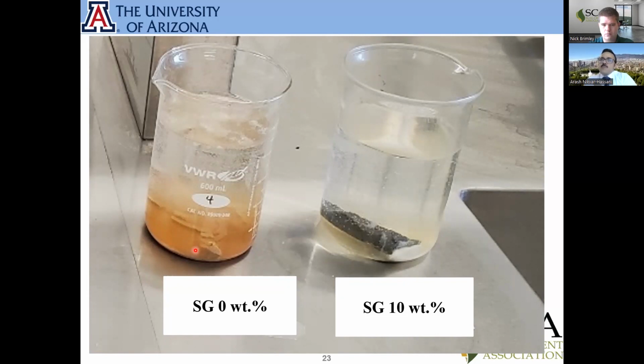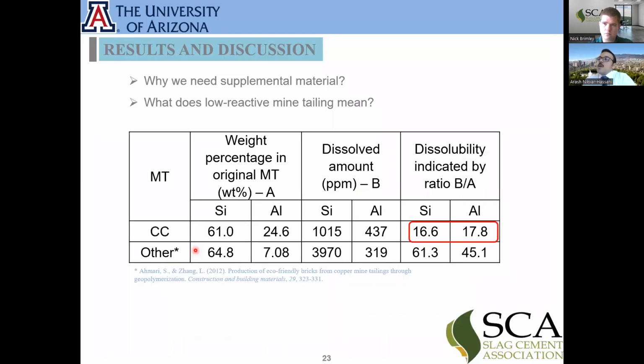What does this mean? This means geopolymer is not good? No. This means that actually there was not much geopolymerization happening. Basically, you had the silica gels holding the mine tailing particles together. And what is the reason? Two things. First, as we discussed, the mine tailings are very crystalline material, with the XRD patterns we showed. Then, these tailings we brought from an abandoned tailing dam. That means the dam closed 20 years ago, and a lot of weathering happened on these tailings.